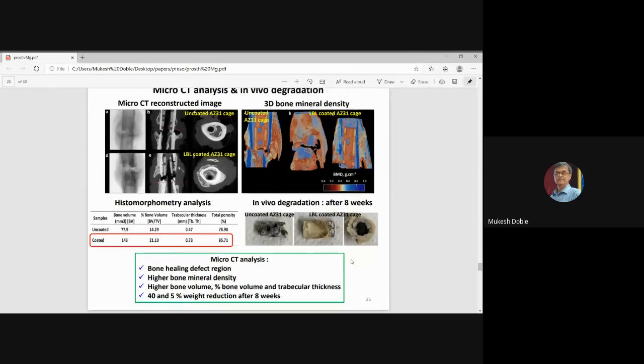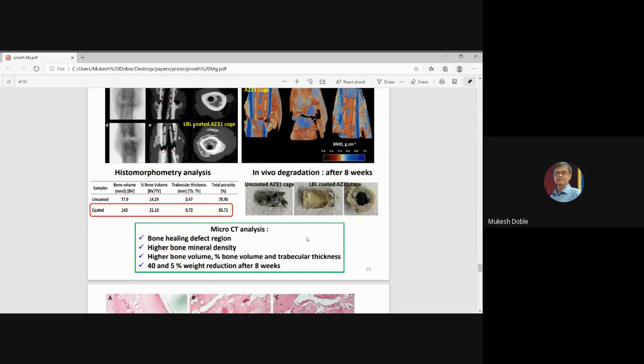We want to reduce the weight loss because we want the material to stay in until the bone gets completely healed, actually. So we looked at that. The uncoated material, the degradation in 8 weeks is 40%, whereas with the coated, it's only 5%. Okay, so again, the coating has helped.